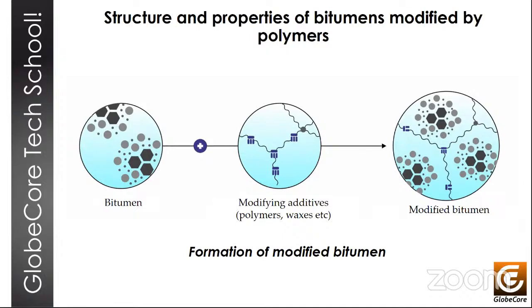And the process of destruction of such composite materials begins with the growth of microcracks. And then, upon encountering a particle of high modulus rubber or polymer, this process slows down, then decreases, and then stops altogether due to the relaxation of overtension at the crack tip.